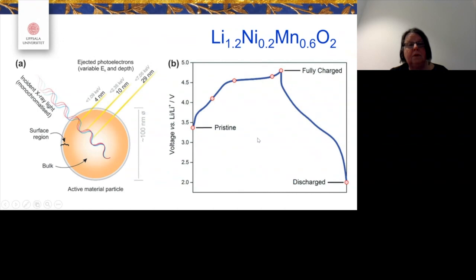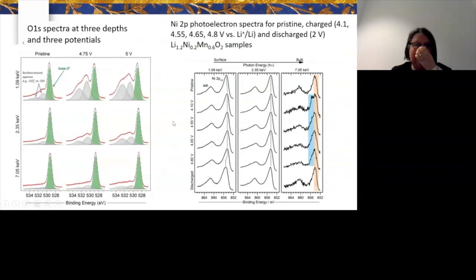You have to repeat the samples so that you really know that you have some kind of statistics on it. So it's very time consuming. So going to an operando situation for this kind of photoelectron spectroscopy would be a dream situation. Of course, we always transfer these samples very carefully from gloveboxes to spectrometers. We have built several chambers to do this exchange and played with this a lot. And in this case, you can see that we can look at the oxygen spectra both as a function of the potential, where we have taken our sample, and also at the depth.